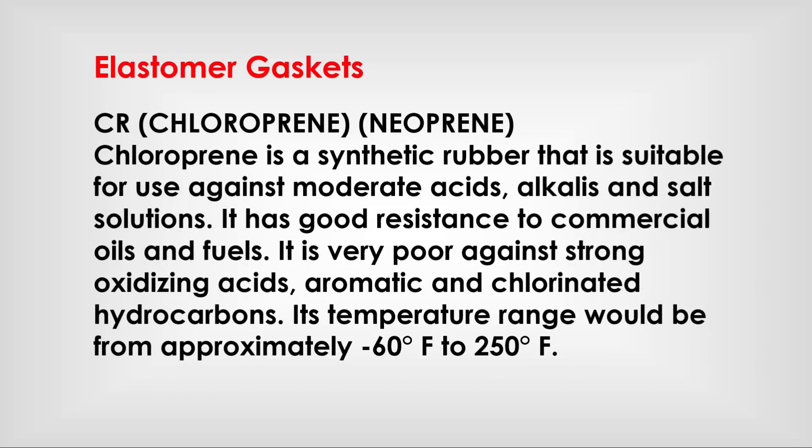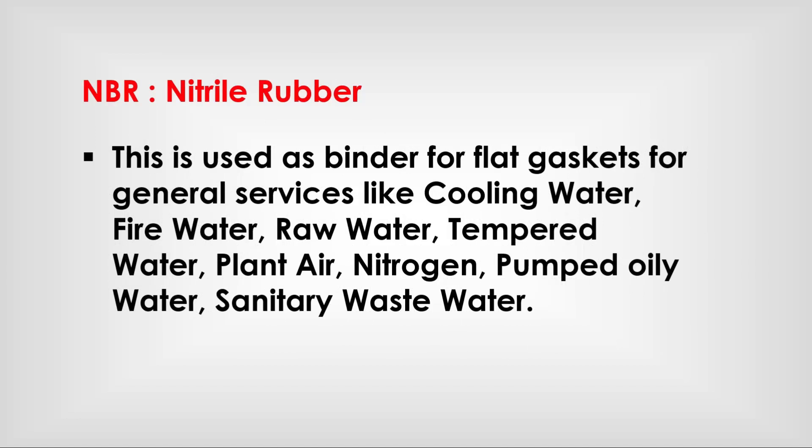Chloroprene is a synthetic rubber suitable for use against moderate acids, alkalis, and salt solutions. It has good resistance to commercial oils and fuels, but performs very poorly against strong oxidizing acids, aromatic, and chlorinated hydrocarbons. Its temperature range is approximately -60°F to 250°F.